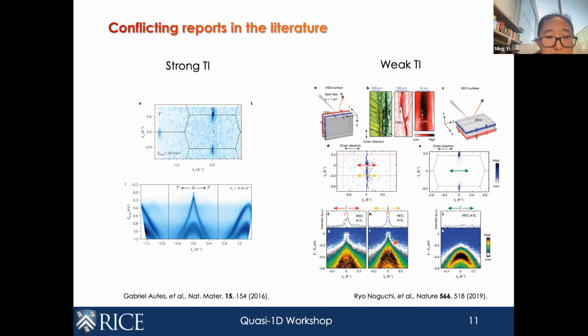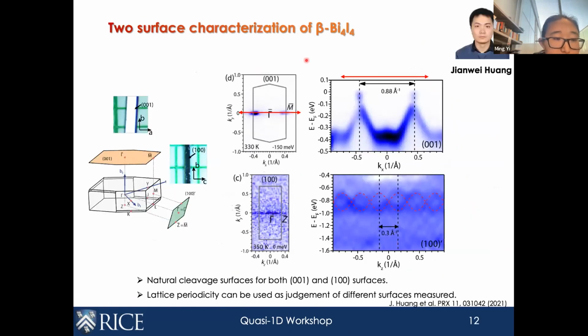So here we wanted to observe for ourselves what really is the topological state of the beta phase of bismuth iodine. And because of the very nice large single crystals that we obtained from Bing's group, we were able to directly measure and distinguish the 100 surface from the 001 surface just with regular ARPES. And you can see that the Fermi surface measured on the 001 surface has bright spots, whereas the 100 surface has this one-dimensional feature, right?